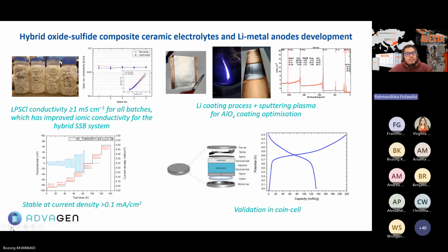Okay, that's for the NMC 811. And the next is the hybrid oxide sulfide composite ceramic electrolytes and lithium metal anodes development. Here, this is what I mentioned in the beginning, that in the Advagen project, we developed the LPSCL. We can reach LPSCL conductivity of more than 1 millisiemens per centimeter for all batches, which has improved ionic conductivity for the hybrid solid-state battery system.